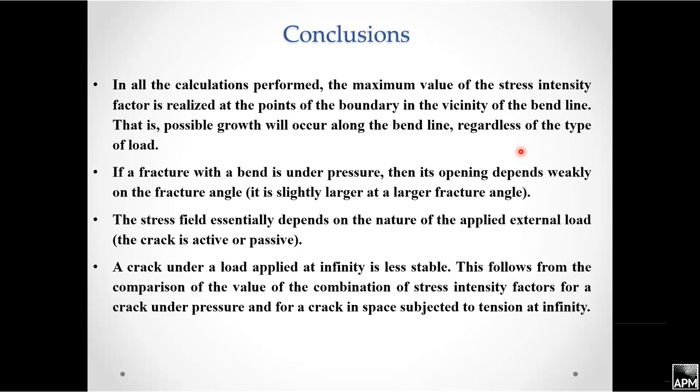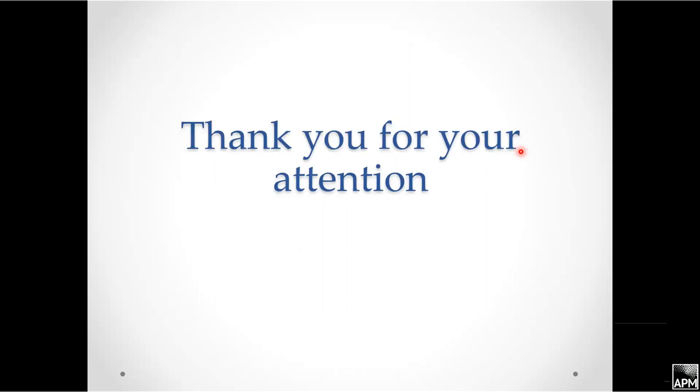If a fracture with a bend is under pressure, then its opening depends weakly on the fracture angle. And the stress field essentially depends on the nature of the applied external load, and the crack under load applied at infinity is less stable. It follows from the comparison of the values of the stress intensity factors for a crack under pressure and for a crack in space subjected to tension at infinity. Thank you for your attention.